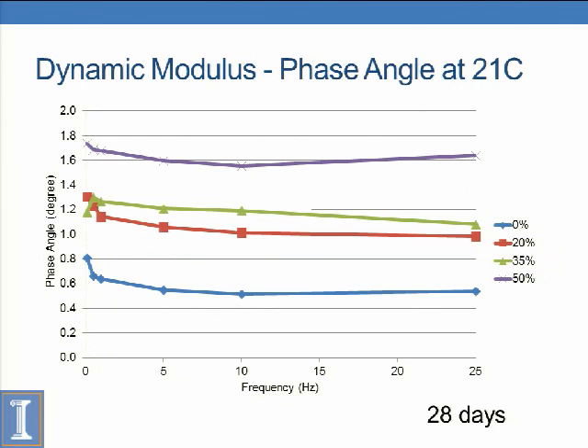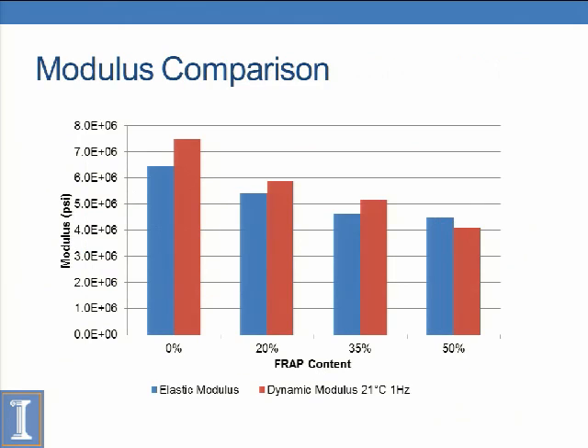Similarly, from that test, we have the phase angle we measured, so 0 up to 50. We can see that because it was concrete, it's a pretty low phase angle, indicating it's an elastic material. But as you add FRAP, you have slightly greater viscoelastic properties, but really, with a degree change of, say, 1 degree, it's not very significant. Just comparing dynamic to elastic, typically dynamic modulus will be a higher value, which for the most part is what we saw, except for the 50% mix, where we saw a higher elastic modulus versus dynamic.